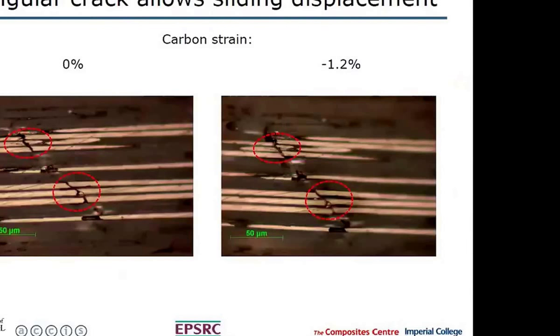It could be quite interesting, but at the beginning of the program, we did quite a lot of work on discontinuous material. Now, if you look at the ply level, discontinuous material, then we find that the response is limited. The amount of pseudo-ductility we can generate is relatively low because you're relying on a lot of strain between the fragments to get a significant amount of strain. So the amount of pseudo-ductility was relatively limited, and also we saw significant drop in modulus because of the discontinuity. So from that point of view, we thought that wasn't quite so good.